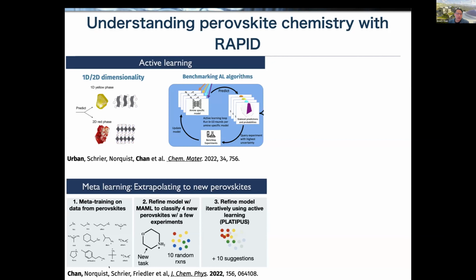So instead, what we can do is train a model that is good at learning new perovskites. In this case, instead of using, say, 100 perovskite reactions to train on a new perovskite, we can say, let's just make 10 different random reactions and see which models can learn that new perovskite very quickly. And so after we use this, for example, model-agnostic meta-learning model, we can then do active learning. So we can ask this model, based on these 10 reactions, what are 10 more reactions that you think will allow you to learn even more? And so we used a variant of MAML called Platypus, because of course a platypus is a mammal, to do active learning in this meta-learning mode. And so this is really exciting, because it offers an ability to do few-shot modeling on these extrapolative problems instead of doing purely interpolation.